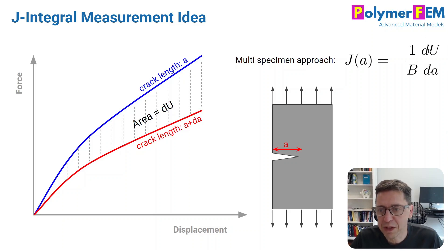That is directly what we can use in the definition of the J-integral. The J-integral as a function of crack size A would then simply be the area between the curves divided by the length difference of the initial crack. And B is the width of the specimen, to make it per unit area. So that's a very clean picture of how this goes in an experimental test.